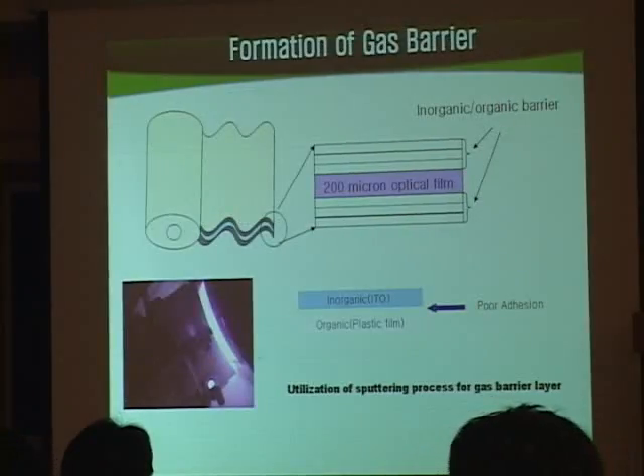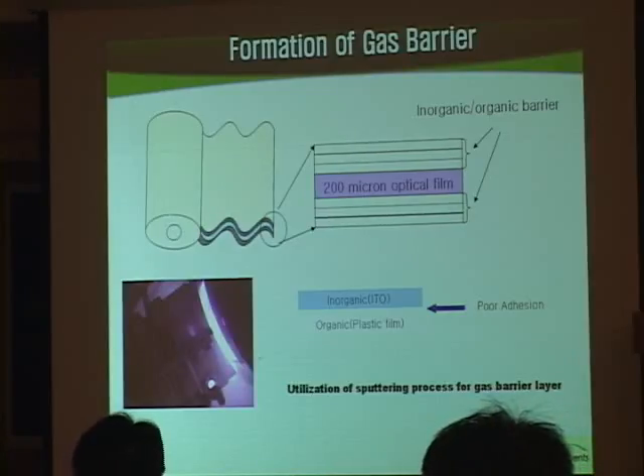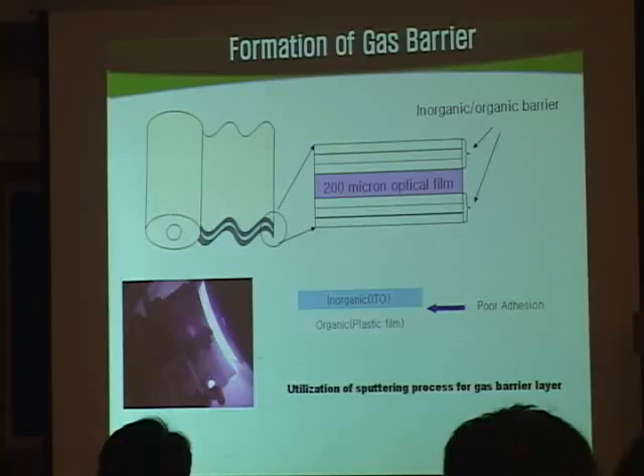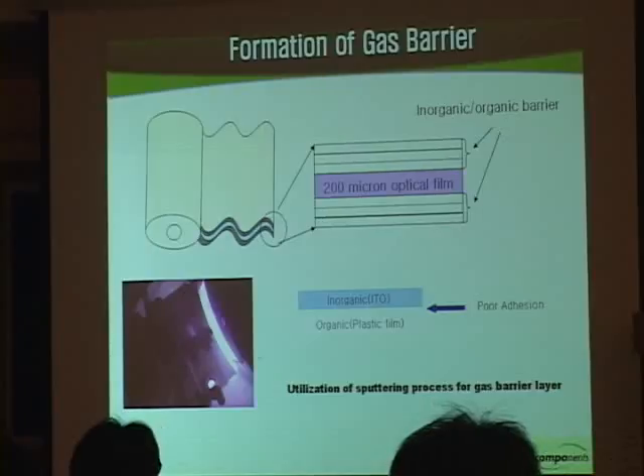about it. But basically our system is 200 micron or 125 micron optical film out of PES, and then do various kinds of coating. This PES has only probably 60, 70 gram per meter square per day WVTR, I mean, gas barrier property. So we still require a certain gas barrier. We apply gas barrier by sputtering. But by putting a sputter layer, usually oxide layers, it certainly improves gas barrier property.